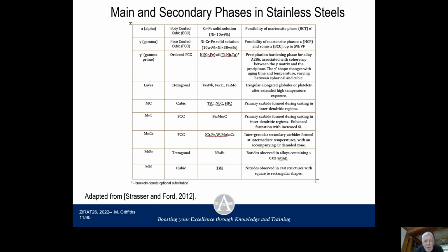It seems to me that we likely have niobium iron Laves phases, as we do with stainless steels, but there are two different camps, and some people believe that they're ZrFe2 Laves phase, even though there's never been any evidence for those. So these are the Laves phases that one might find.